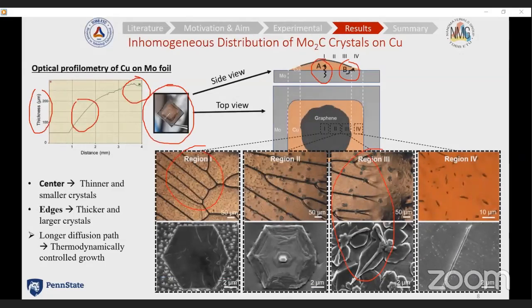So therefore, most of the molybdenum species first diffuse to the surface of the copper and then move to the center of the substrate. And since this diffusion path is longer for the center, for the crystals formed at the center, the attachment of molybdenum to the as-formed molybdenum carbide crystal occurs slowly, step by step. So therefore, hexagonal, thermodynamically stable, thin crystals form at the center. However, at the edges, we observe kinetically controlled crystals, or flakes. And therefore, for the consistency of the results, I'll be showing the crystals that were taken from the center of the substrate.